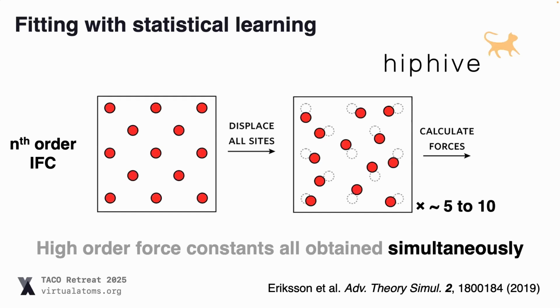So what this package HiPhive does is an approach where you can use statistical learning to displace all of the sites in a structure all at once and use an algorithm such as compressed sensing to fit all of the force constants simultaneously. So it means that rather than having thousands or tens of thousands, you can now just get away with 5 to 10 structures and still obtain pretty reasonable force constants. So it's a very powerful method.